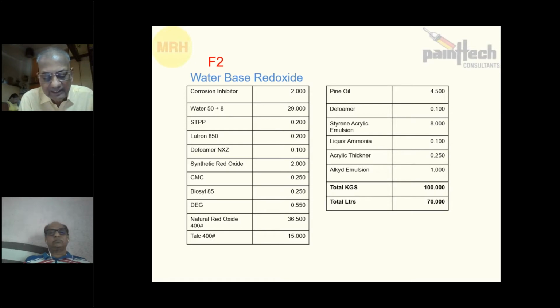This Alkyd emulsion, I punch only 1 or 2 kilos into our regular water-based high TG emulsion. What happens? Being ultimately polyester, it takes care of the adhesion problem - solved. Your substrate wetting problem is solved. And breathability problem is solved.